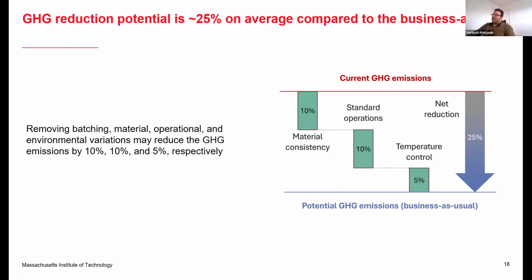At the end, we have translated these variations into GHG savings, and we found that by removing the batching, material, operational, and environmental variations, we can reduce the GHG emissions by 10%, 10%, and 5% respectively. And in total, the GHG reduction potential is about 25% on average for different specified strength mixes.